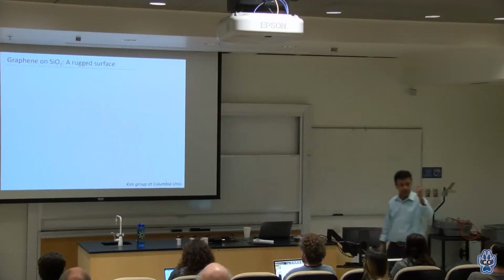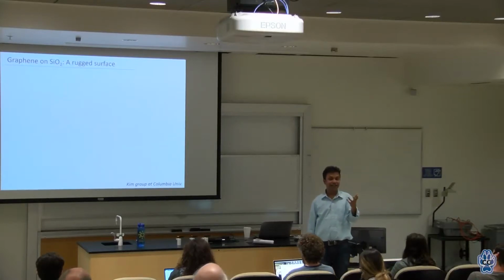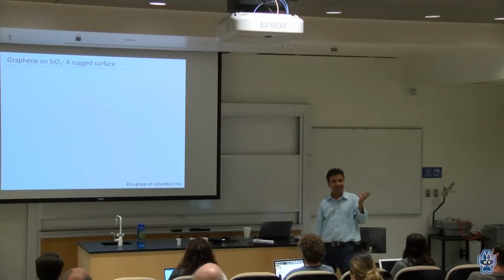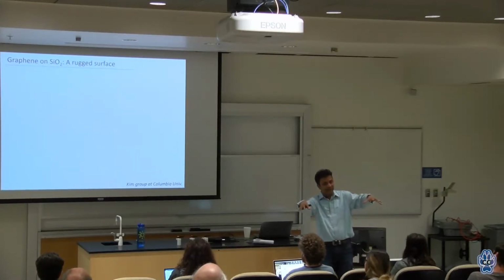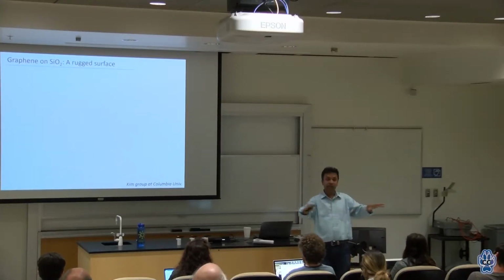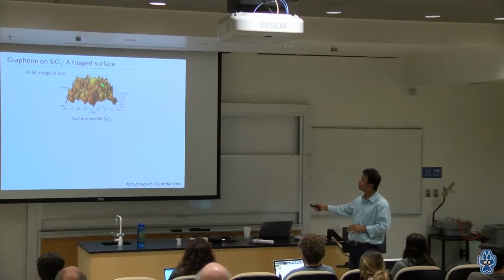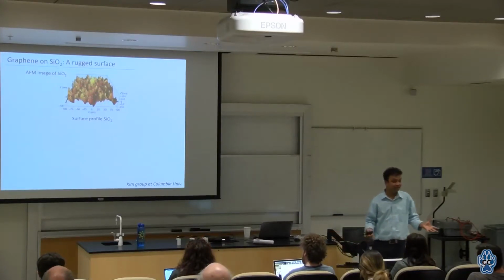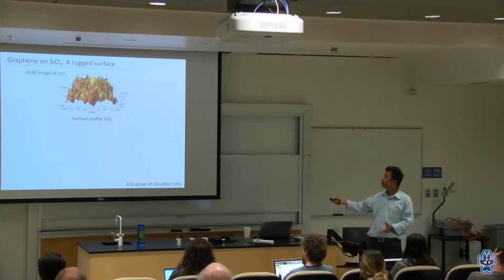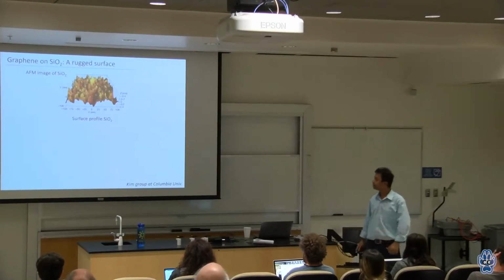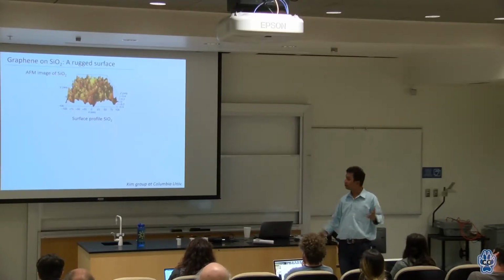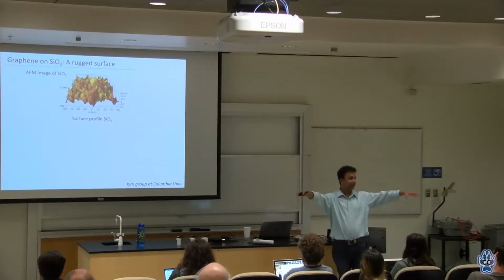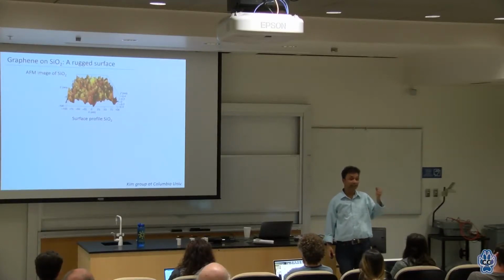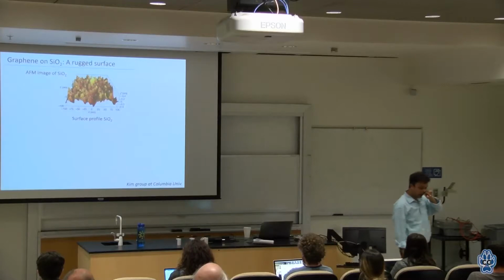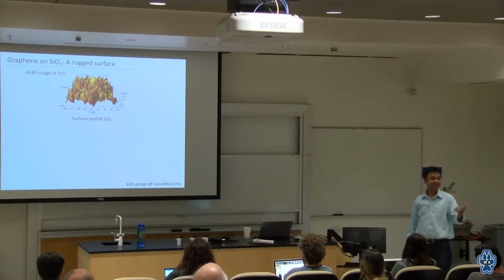Now I'll talk about, as you say, people first studied graphene on SiO2, silicon dioxide, right? But when you're putting one atom thick materials, you need a very high quality surface. If you look at SiO2, it looks like a ragged surface, and the variation is of the order of 0.4 nanometers. So what do you need? You need to improve. If you put graphene there, what will happen? Graphene will also be sitting on a ragged surface, and the electron will feel lots of resistance coming from the materials.